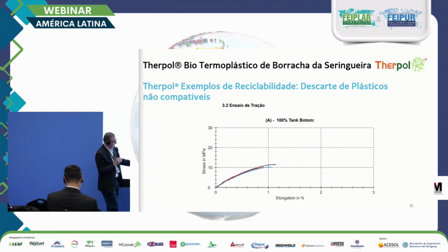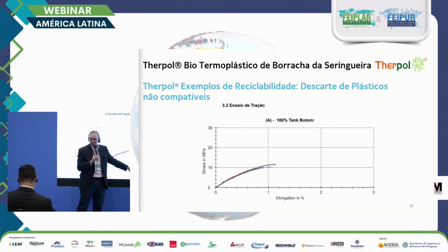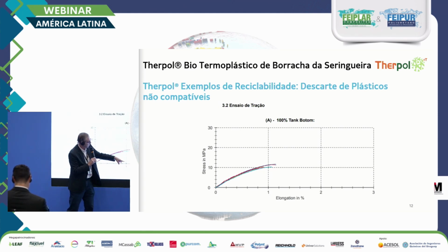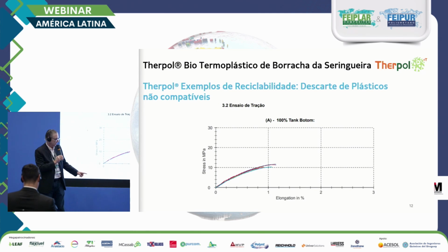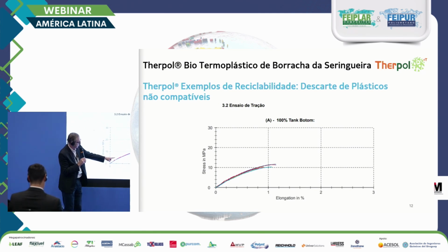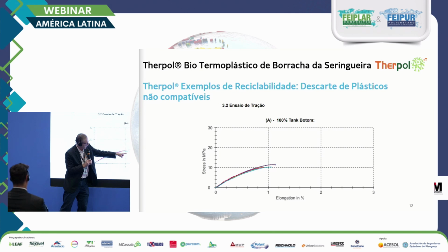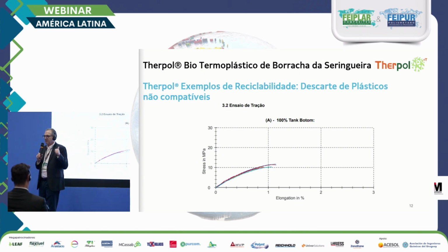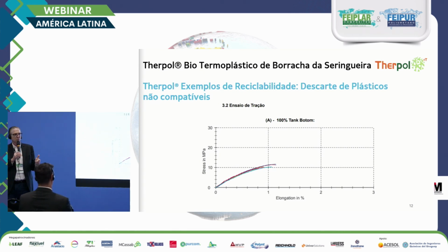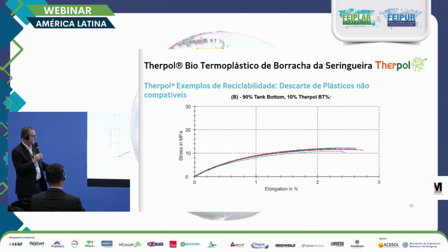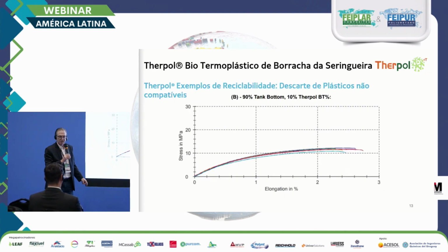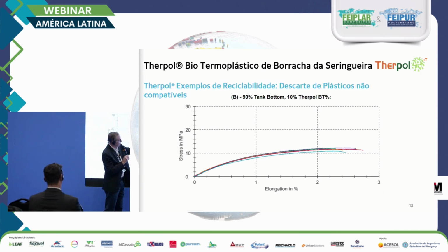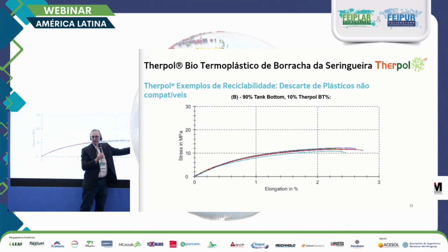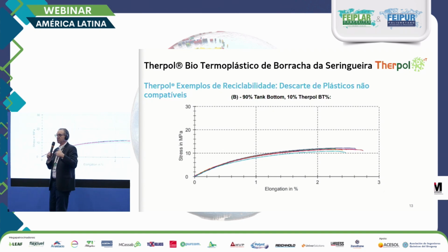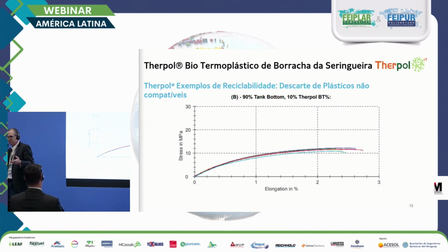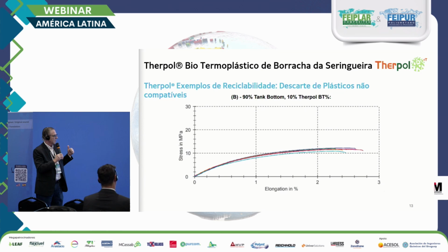So 100% of the tank bottom, this is extension. More than 1% it breaks. So we put 10 samples, and none of them went above 1 point something. Then on this one, we put 10% of Therpol. And look at where it's going. We were here with 10% of Therpol. It extended much more. So it starts becoming more resistant, more flexible because of the rubber.